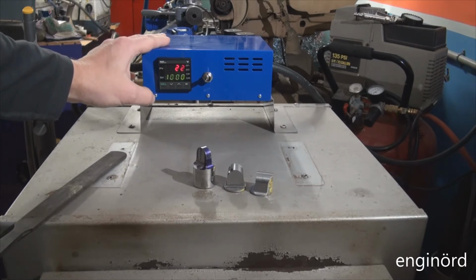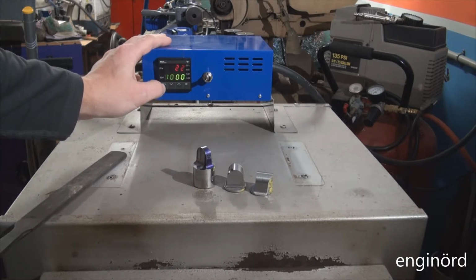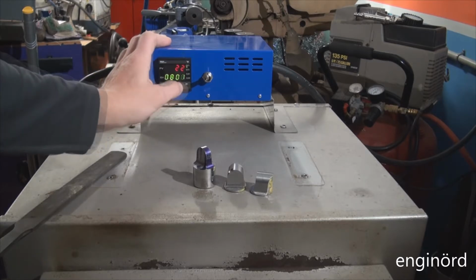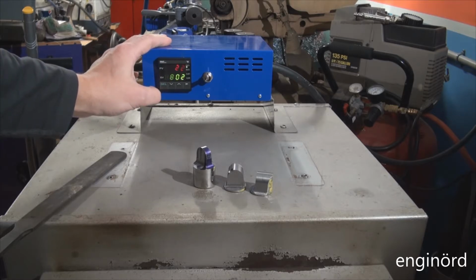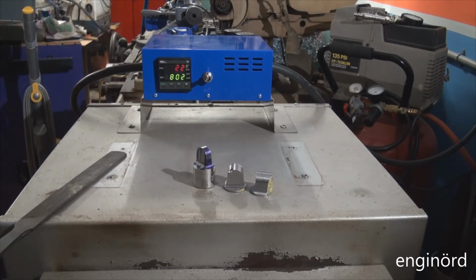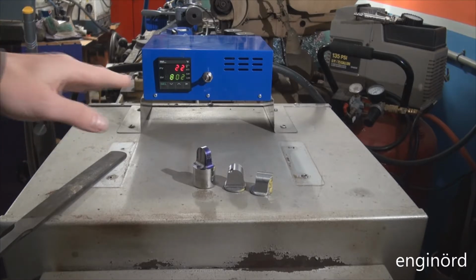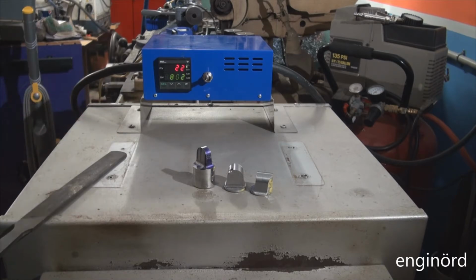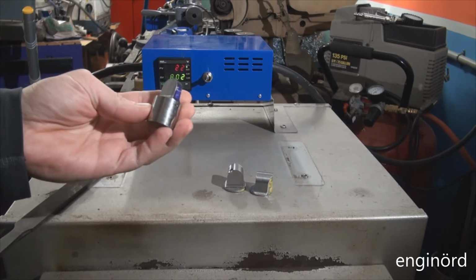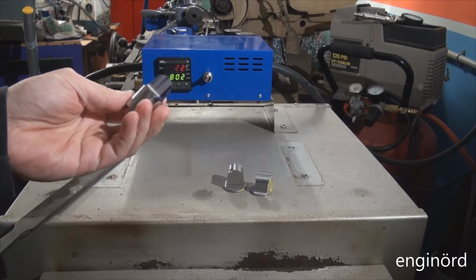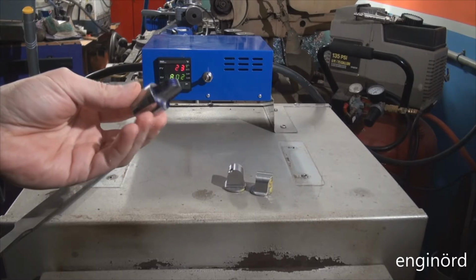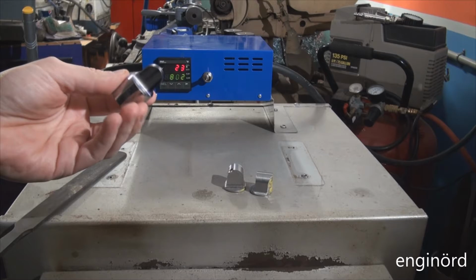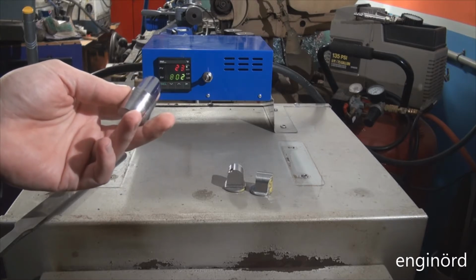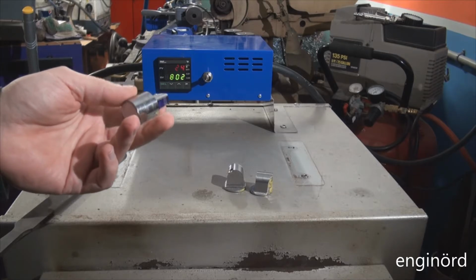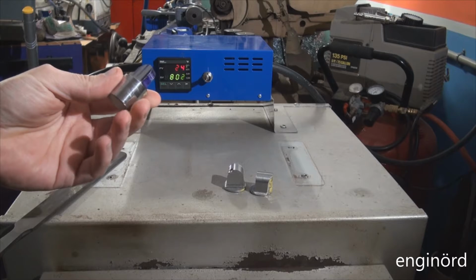Just turned on the kiln, and we're gonna set the temperature to 802 degrees Celsius, just like that. So now the kiln is on. I spent an hour and a half yesterday trying to get the ramp and the dwell cycles properly done, because this O1 tool steel doesn't like to be heated too fast. I don't know if it leads to stress cracking or what the failure mode is, but they recommend about 222 Celsius per hour, or 400 Fahrenheit per hour, heating cycle.